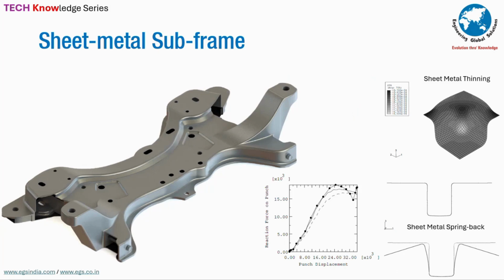When we are doing these kinds of analysis, we need to look at the sheet metal thinning that would happen. A 10% thinning on a 3.4 millimeter thick plate brings down 0.34, right? Which is 3.06. But you have done a nominal analysis with 3.4. So there are two stages that you need to look at.